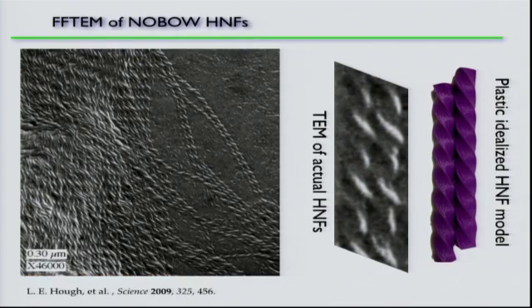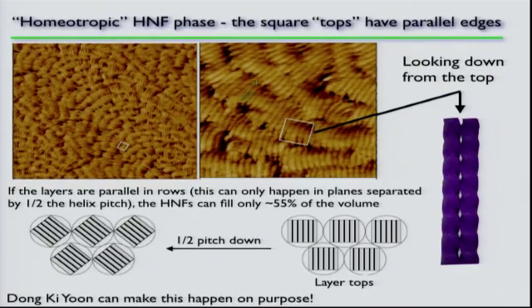All right, and here's the freeze fracture TEM, showing what they look like. This is glass. Here's the filaments on the surface, and here's a close-up of the filaments, and these are plastic models of these things. So we think this is looking kind of like this, and that's what you're seeing in the TEM. And here's this beautiful homeotropic AFM image of a homeotropically aligned B4